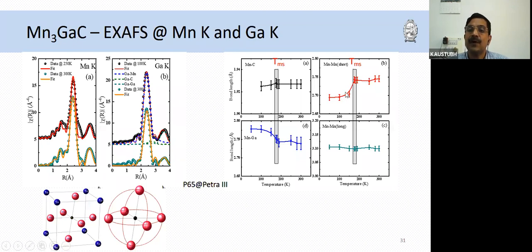from 2.75 to about 2.70 angstroms. So what we thought by looking, we know that if there is a manganese distance which is lower than 2.75, then it almost always aids antiferromagnetic order, whereas if there is a distance which is higher than 2.75, it gives rise to ferromagnetic order.